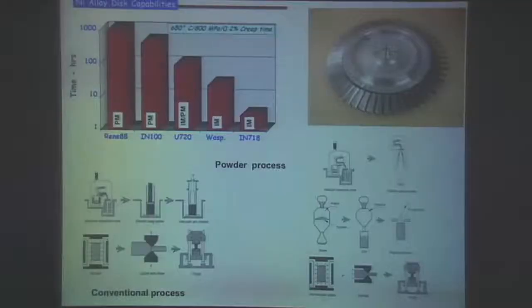Aircraft engine discs are also made by complex processes. They're no longer made by conventional ingot metallurgy processes. They are made by powder processes, to prevent microsegregation during solidification when you have a very large amount of alloying additions. Powder processes allow you to cool fine powder particles extremely rapidly to prevent microsegregation. And then you can extrude the powder and HIP it and so on to get the final shape of that disc. And so the properties of materials have improved enormously over the years.